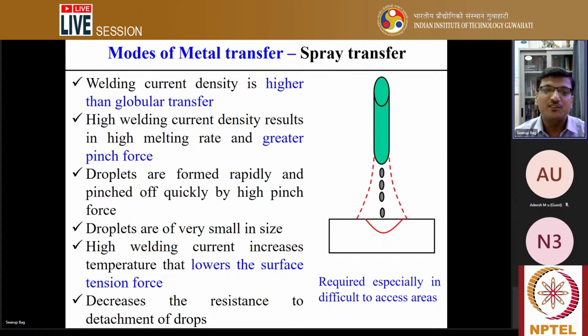So when there is a competition between these two and a greater pinch force is there, then more droplets will be created, very rapidly, and pinched off very quickly because of the high pinch force. And since the droplets are formed very rapidly in a very localized area, the droplets are usually very small in size. And this is only possible if you use a high welding current.